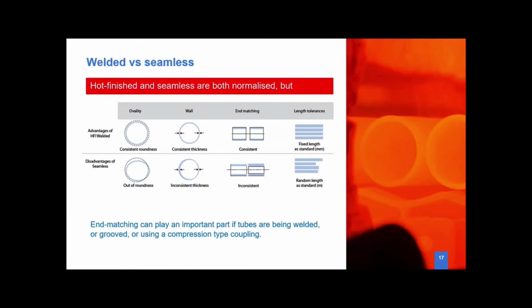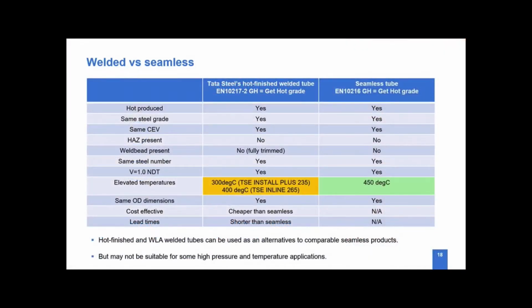One of the advantages that welded has over seamless is that a welded tube, because of the way we form it, we have very tight control of the tolerances. So when it comes to ovality and consistency of wall thickness and end matching, a welded product will always be seen as being technically better than a seamless tube, which unfortunately can suffer from out of roundness and inconsistencies on the wall. However, we know that because of the manufacturing process route which seamless follows, because it's being extruded, its grain structure is aligned better to that within a welded steel chemistry, which means that a seamless tube can be able to withstand higher temperatures than a welded tube.